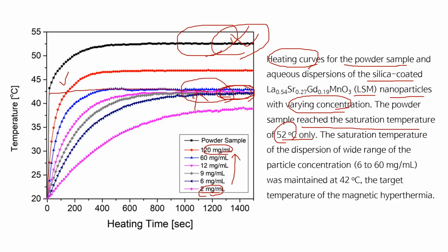The saturation temperature of the dispersion for a wide range of particle concentration, 6 to 60 milligram per milliliter, up to here. So this here, right? So saturation temperature for these samples was maintained at 42 degrees centigrade, around here. That is the target temperature of the magnetic hyperthermia.